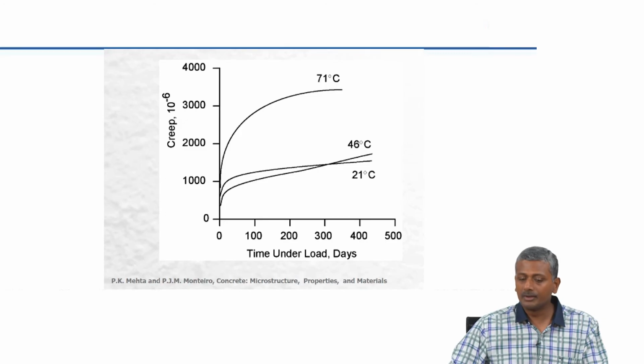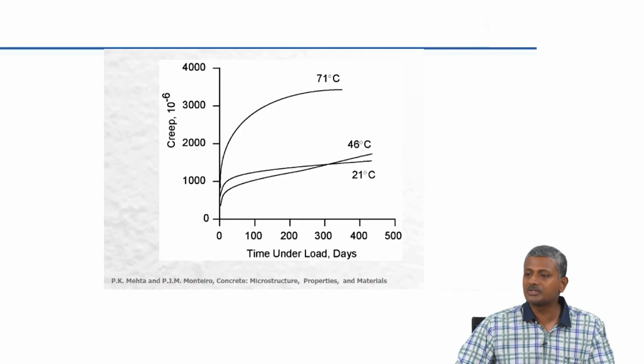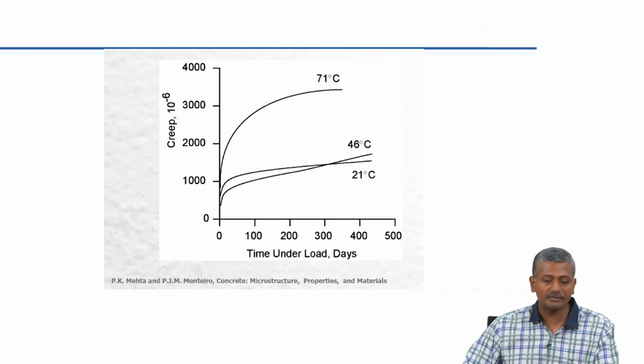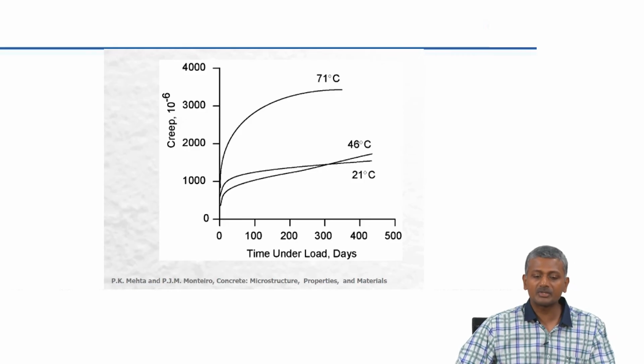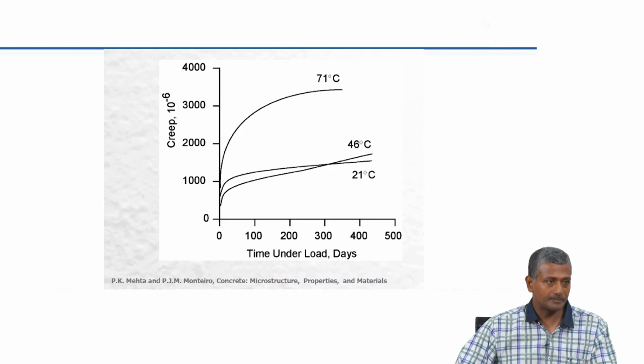Again, this is showing you results which are there in your textbook. At 21 and 46 there is not that much distinction in the extent of creep, but when the temperature is very high, up to 71 degrees, you can see that the creep is changed by a factor of nearly 2.5 to 3. So, that is a major increase in your creep.